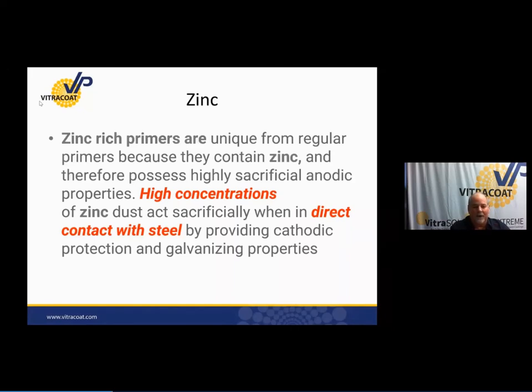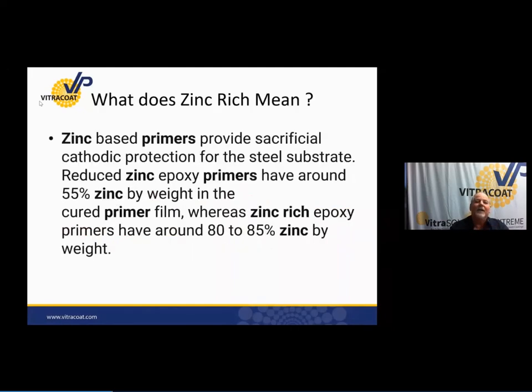Zinc rich is a very common phrase used with liquid coatings. And if you think about liquid coatings, it means that we're putting in an abundance of zinc in that formula, and we're spraying it using the vehicle of water or solvent that evaporates off, leaving that film which contains a very high percentage of zinc. 55% is probably on the very, very low end of what you need to be sacrificial in order to perform well. 70, 80, 85% zinc by weight. That's where you really get to the point where it's becoming the cathodic result that you need from the zinc within the coating itself.